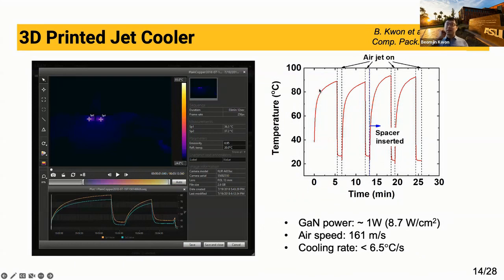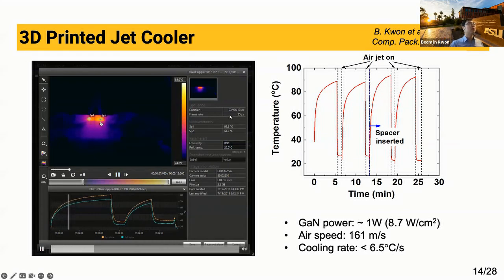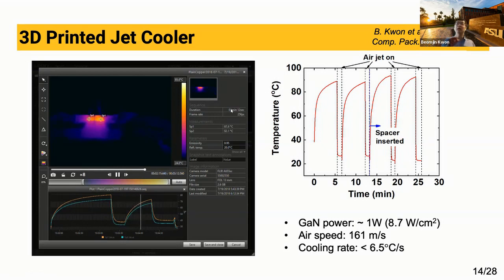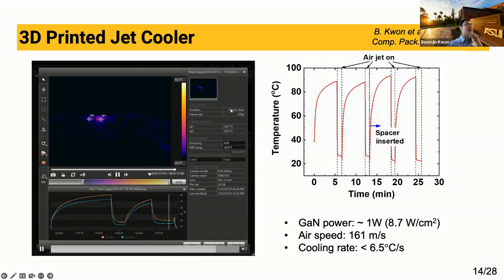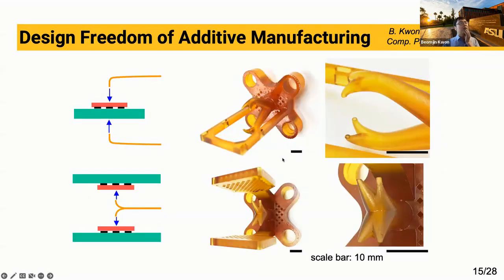So I want to show a video that demonstrates the performance of our jet cooler. So this image was taken by infrared camera. And when you operate the transistors, now the temperature increases up to slightly above 90 degrees C. And then when you inject air jet, the temperature almost instantly drops to room temperature. But as you stop the jet flow, then temperature increases again. But if you inject the air jet again, the temperature drops to room temperature almost instantly.